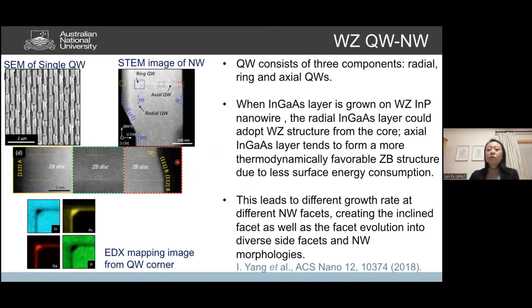On the radial surface surrounding the indium phosphide, the radial indium gallium arsenide layer quite happily adopts the wurtzite structure from the indium phosphide core. However, on the top facet, because of the surface energy, which is lower, the indium gallium arsenide really wants to form a zinc blende structure. Because of that, we get different growth rates at different facets, and that creates this inclined facet, and that evolves into all these different types of nanowire shapes.